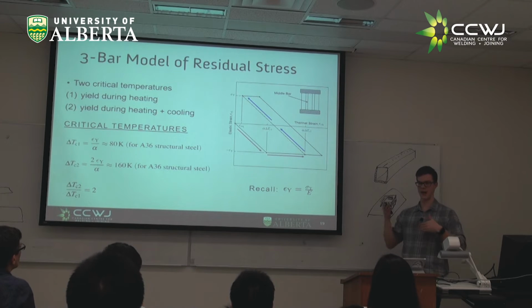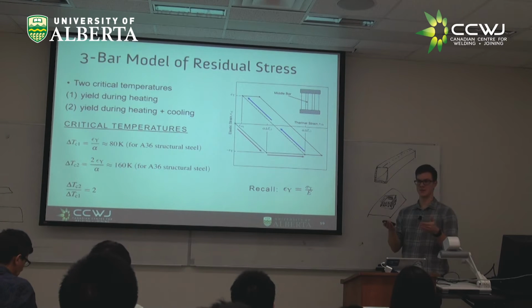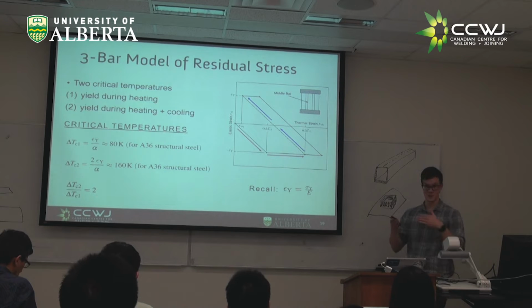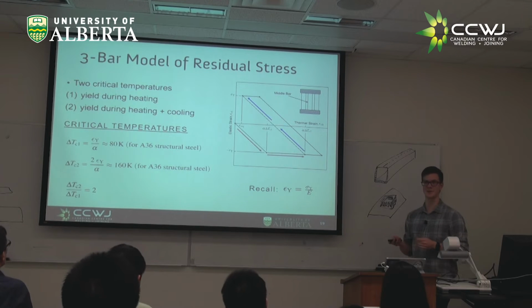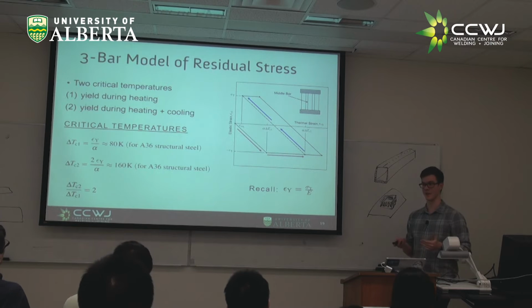Does that make sense? You have a higher strength material. You need more thermal strain to produce yielding. So the region that you have thermal stresses becomes smaller. Now the stresses in that region are going to become larger because there's still yield magnitude and your material is stronger, so the stresses are higher, but the region where you have stresses is smaller. So all those complex effects of phase transformations and melting become more significant for higher strength materials because of that.